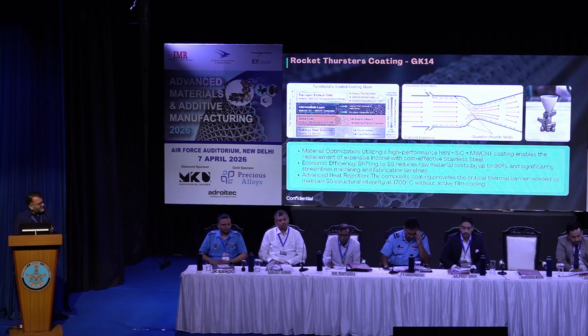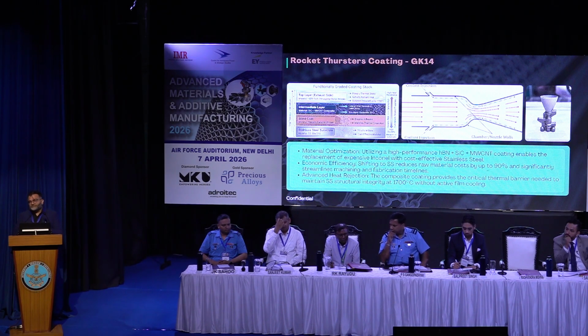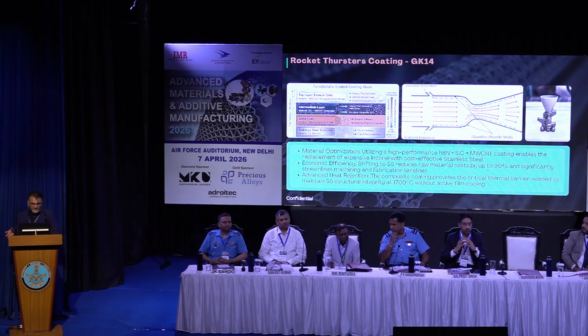So these trials will happen next week hopefully, where we will use stainless steel instead of inconel or nickel or hastelloy, and we'll do a coating, because the whole cycle of the rocket we are designing with the company is around 90 seconds. In 90 seconds it will hit the target or it will consume the whole fuel it has. So the whole coating has to survive 90 seconds. When you use stainless steel, you are able to increase the payload by 10% because inconel is very heavy, and you reduce the cost as well. So these are good solutions: we can use different types of coatings to reduce costly materials and use lighter materials.